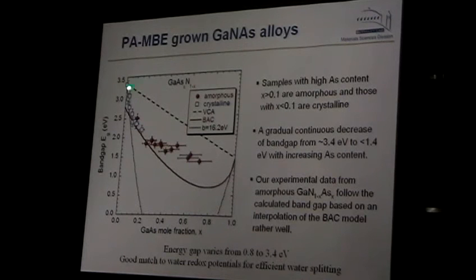However, the point is that our anti-crossing works very well here. Of course, amorphous is a different material. We don't really know how to describe this material. It works very well here. We can explain it because the band gap is going down very rapidly on this side. This part seems to deviate from our predictions, but it's still very interesting.